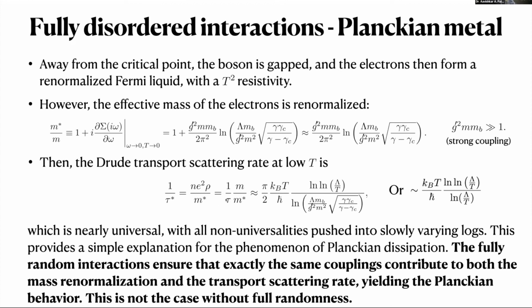So when you define tau star in terms of m star, the interaction cancels and one gets k_B T over h bar times some order 1 number times some logs, which contain all the non-universal stuff. It depends on how you want to cut things off. All the non-universal stuff is shoved into the slowly varying log functions. So one gets nearly k_B T over h bar times some order 1 number. You don't get 10 k_B T over h bar and 100 k_B T over h bar, even though the non-universal stuff can be very different in different materials, because it's within the log. And for this, the fully random interactions are important.